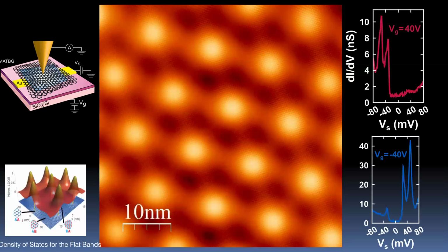Now, when you do spectroscopy, you'll see the flat bands. But even in the images, these bright spots essentially come from the fact that the electrons in the flat bands are localized in the AA regions. This is essentially an interference effect that gives rise to semi-localized electrons in the AA region in real space, and this will become important as we try to think about interactions in this problem.